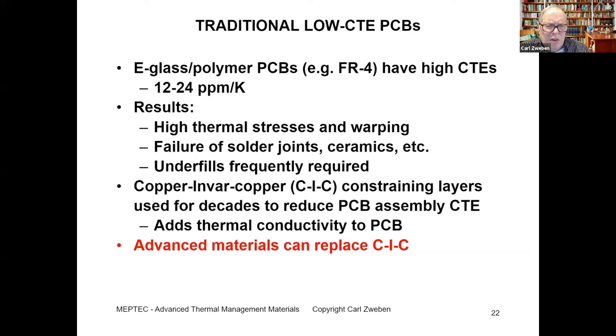If we look at historical usage, for many decades, copper Invar copper constraining layers were used with e-glass printed circuit board to reduce the coefficient of expansion of the printed circuit board. And the copper Invar copper also adds thermal conductivity to the printed circuit board. However, we have advanced materials that can serve the same function as the copper Invar copper, offer higher thermal conductivities and lower densities. And we'll take a look at one example later on.